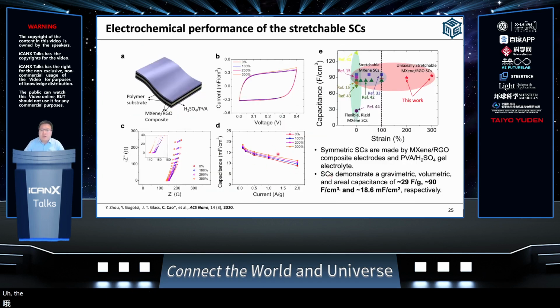The double layer supercapacitors made by the MXene and reduced graphene oxide composite can have very good stretchability, reliability, and excellent electrochemical performance. The applied strains actually had little influence on the electrochemical performance of the device. Carbon nanotube forest is another promising material for developing sensors and supercapacitors. But people before mainly used aligned carbon nanotube films.